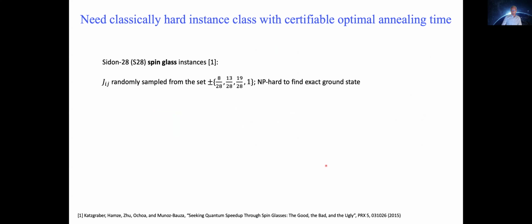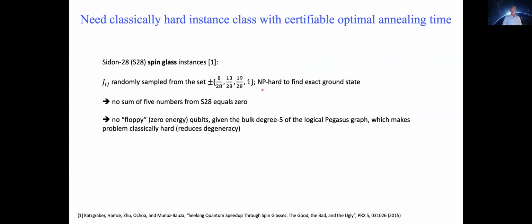Okay. Now we also need problem instances, and I already described frustrated loops and so on, and tunneling gadgets. But in this case, we decided to work with the so-called Sidon 28 spin-glass instances, which were introduced by Katzgraber and company. These are random spin-glass problems. The J's are sampled from this set. And it is known that finding the ground state is NP-hard. And they have a nice property, which is that no sum of 5 numbers from this set equals 0.